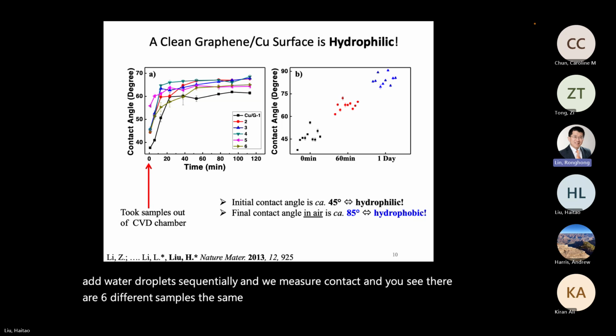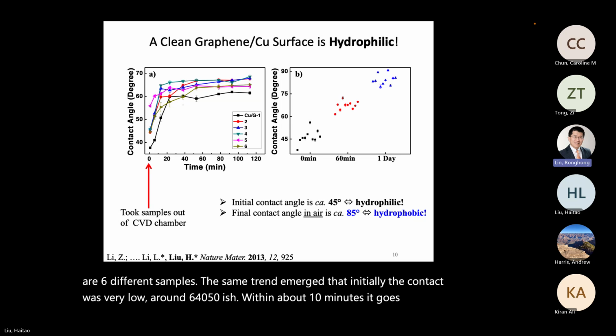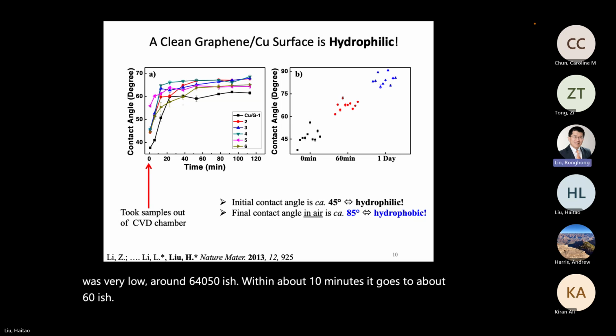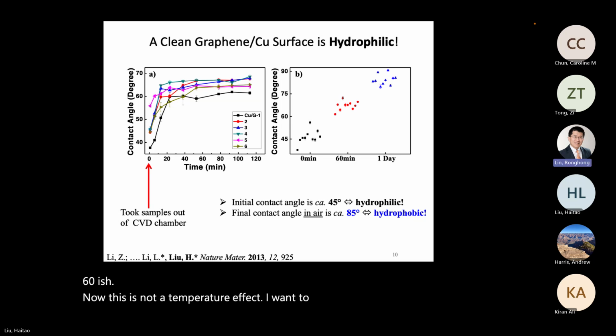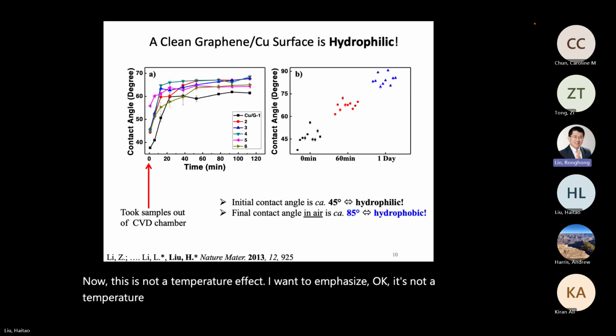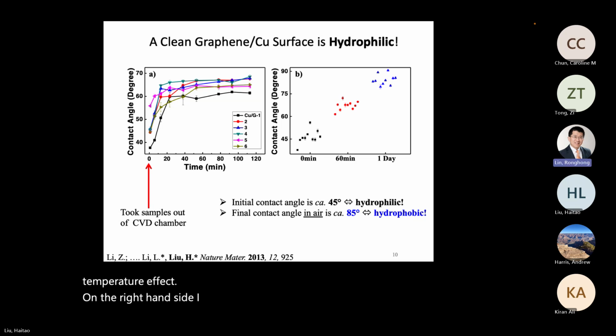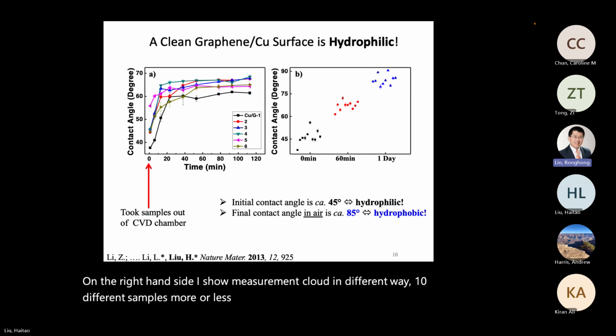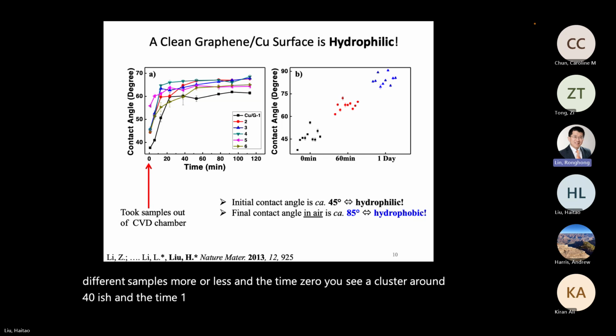The same trend emerged: initially the contact angle was very low, around 40, 50-ish. Within about 10 minutes, it goes to about 60-ish. Now, this is not a temperature effect, I want to emphasize. It's not a temperature effect. On the right-hand side, I show measurement plotted in a different way, 10 different samples, more or less. At time zero, you see a cluster around 40-ish. At time 1 hour, you see about 65, 70-ish. And after 1 day of exposure in air, we got contact angle around 85 to 90.